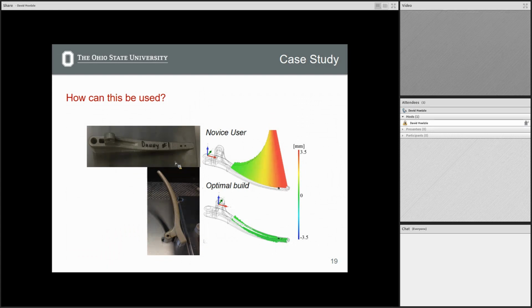And then when you actually remove this via wire EDM, this is the distortion profile as measured by CMM at the tip. And just to show you, this is off the page. This actually distorts around 3.5 millimeters. That's pretty much not within any manufacturing spec, 3.5 millimeters. So you can imagine the amount of residual stress that's built up in here to get this pretty thick piece of stainless steel to distort all that much.